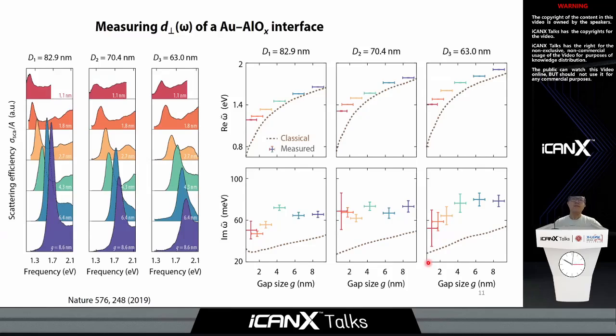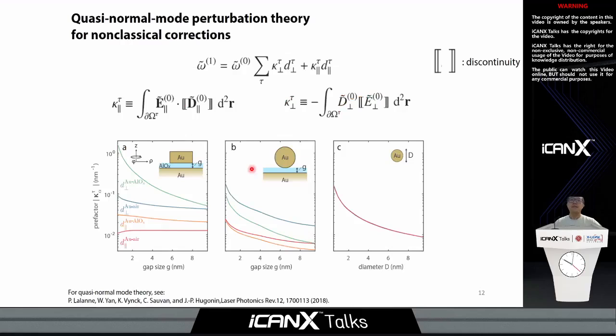The last piece to complete this picture is to use the quasi-normal perturbation theory, which connects our measured frequency shift, omega-1, with the mesoscopic d parameters via a set of perturbation strengths kappa. This kappa has a clear physical meaning: it corresponds to the classical energy difference across a given interface. We calculate these perturbation strengths for different structures, and we find that the perturbation strengths of our experimental choice are much larger than those of other widely used platforms. This justifies why we were able to see such a pronounced non-classical shift in our measurements.